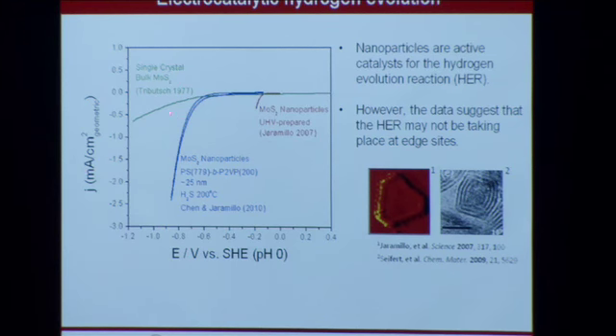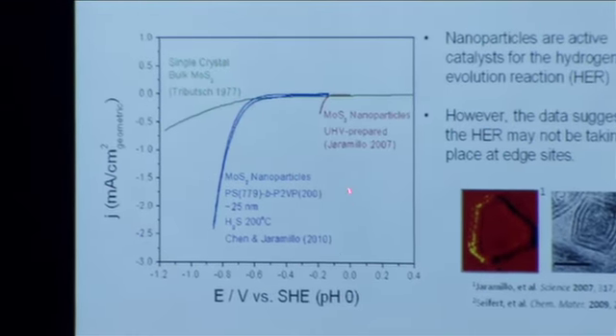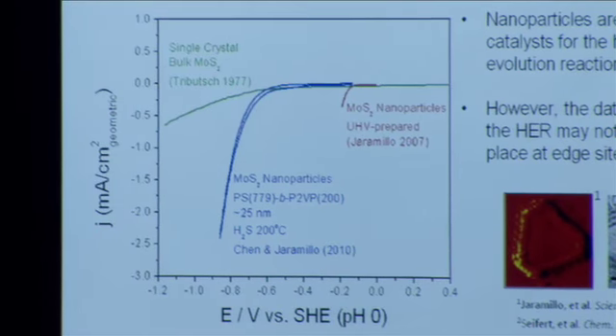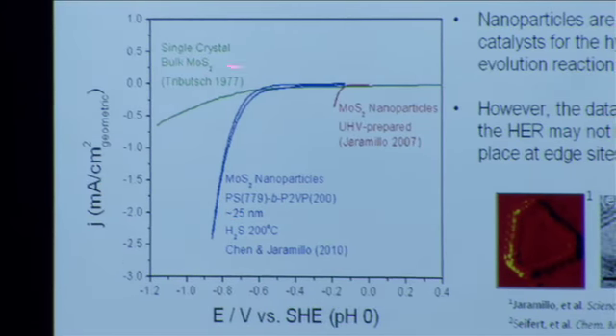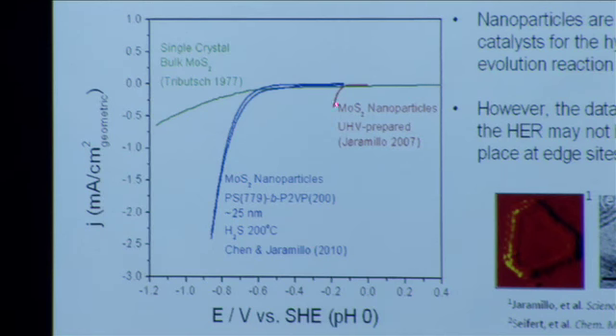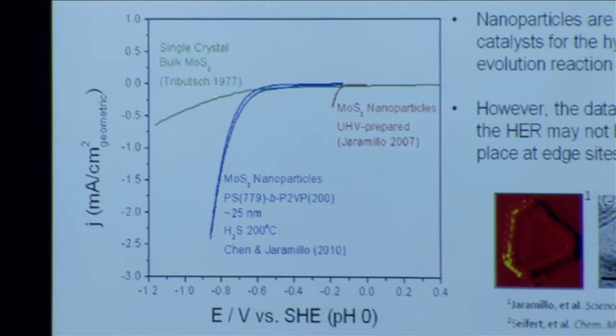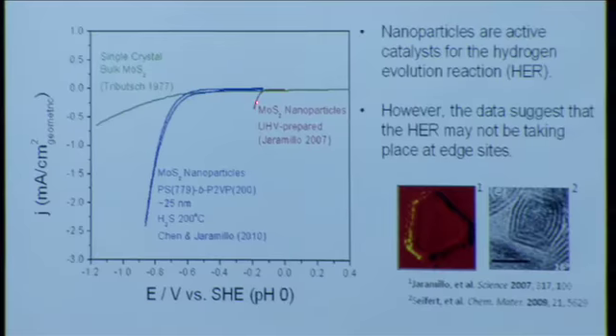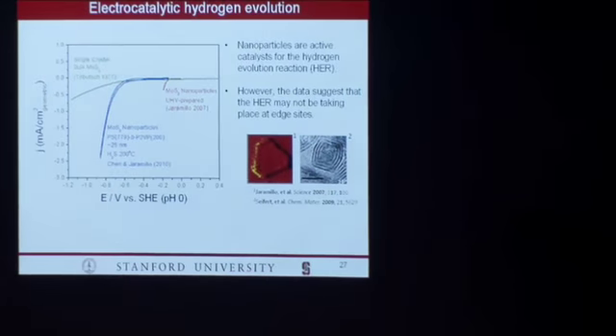I want to point out this is a cyclic voltammogram in which you're looking at potential versus the standard hydrogen electrode at pH 0, which means that 0 volts is the thermodynamic limit for reducing protons to H2. We're looking at 3 pieces of work. This is a single crystal molybdenum sulfide that was published by Tributsch in 1977. A few years ago during my postdoc, we looked at molybdenum sulfide nanoparticles that were produced in vacuum, particles that look just like this by STM. And you can see that these are extremely active because the hydrogen evolution current is very close to the equilibrium potential of 0. And these are the nanoparticles, the 25 nanometer variety that we've prepared and impregnated onto that transparent conducting oxide. You can see that these are certainly active for hydrogen evolution, though not quite as active as these UHV prepared nanoparticles, which we think might have to do with some folding.